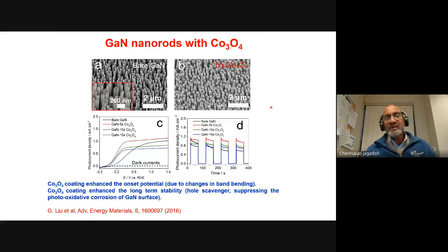You have to use plasma etching. But in photooxidation or photocatalysis conditions, photocorrosion still takes place because of the accumulation of holes. By putting cobalt oxide on, which also acts like a co-catalyst and scavenges the holes, we are able to get a very stable performance from these structures.